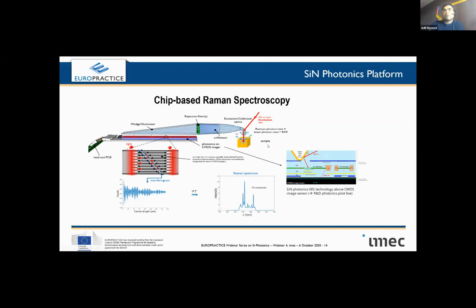It's a slide which I took from one of my colleagues. What you see here is one of the demonstrators where when a light is made incident on a sample, usually an organic sample, it can even be your tissue or skin, the scattered light is collimated and put directly on top of the chip. The chip in this case, as shown here, is a CMOS imager chip on which different layers of oxide, metal, and silicon nitride have been deposited and etched and patterned, including some fancy things like this copper structure, which is used as a mirror to put light in.